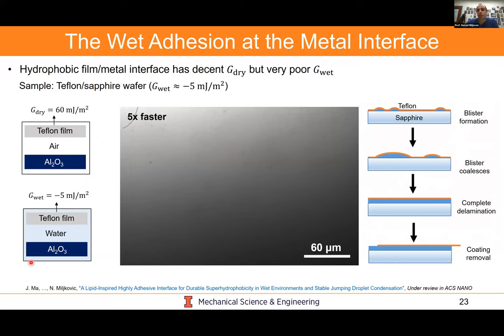Some people will ask, what does it mean to have a negative wet adhesion? It means that water will preferentially want to displace the Teflon. So if you condense, water will preferentially get underneath the coating and want to stay there. Schematically, because the video is not playing, blisters will form very quickly, the coating itself will float, and it'll be removed completely by the condensate. And this is not good. Even though you could achieve a coating with fairly good dry adhesion, it gives you very poor characteristics during condensation.